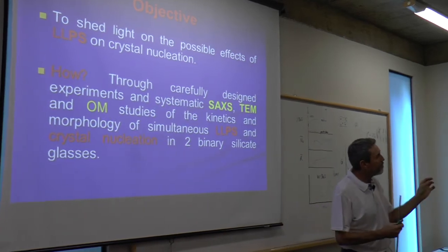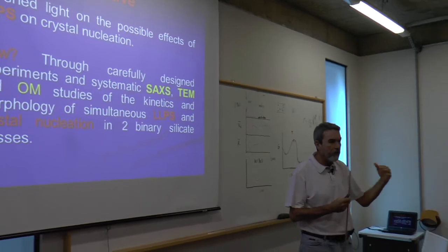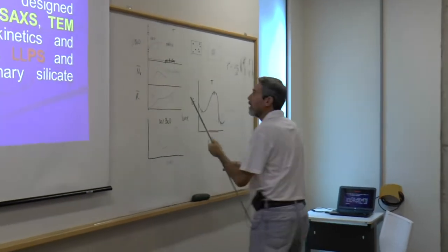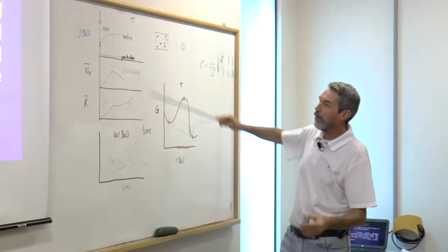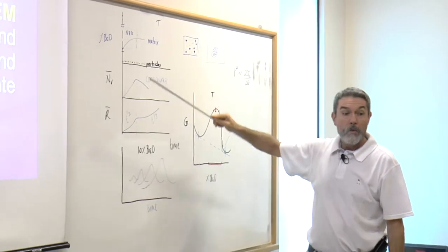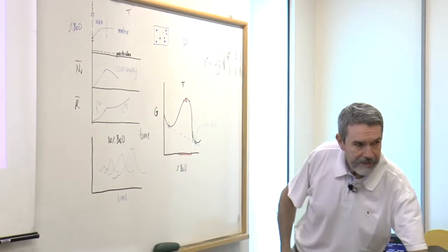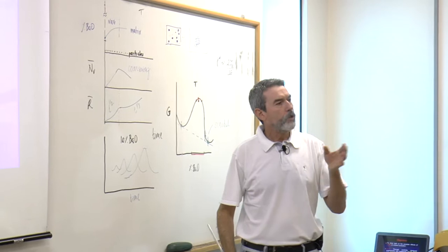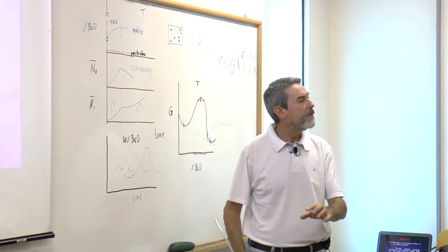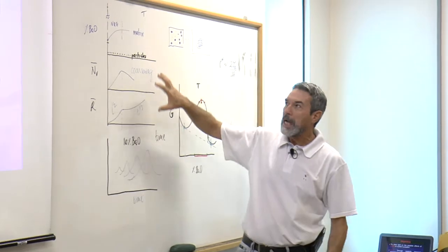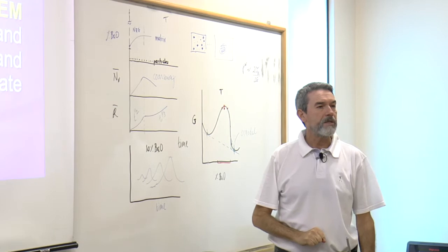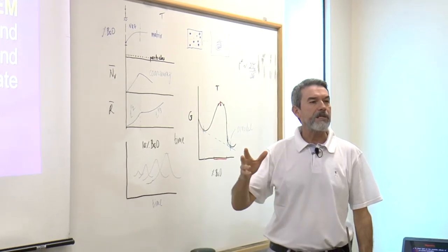So we had a series of glasses, heat treated above TG for some time, and we followed this type of kinetics with techniques which allowed us to decouple liquid phase separation from crystal nucleation, because simultaneously with liquid phase separation, crystal nucleation takes place.